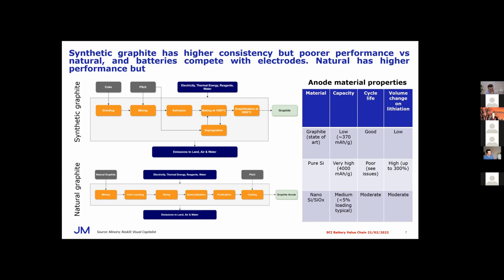The natural graphite route is a rather more simplified value chain than we saw for cathode materials. Here we take natural graphite, typical upstream mining, and then a leaching phase to strip out impurities. And then what generally tends to happen is a spheronization step to round the flakes, and then they're purified and coated with a substance. And that tends to form your graphite anode. So between synthetic graphite and natural graphite, there are some crossovers, but effectively they result in a similar type of carbon structure that would form your anode.